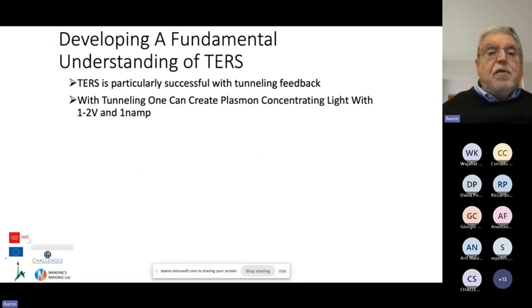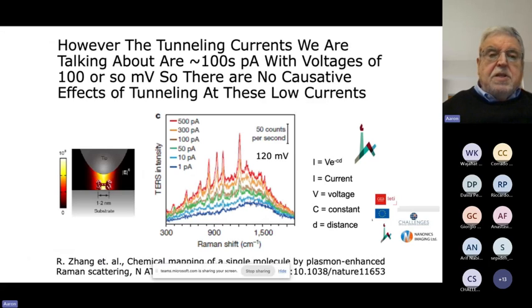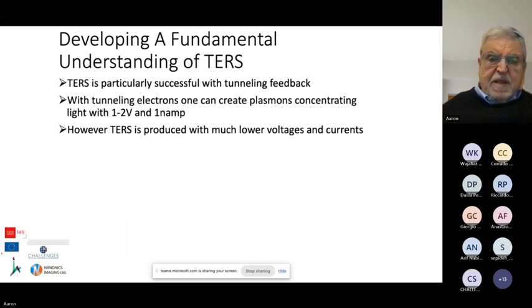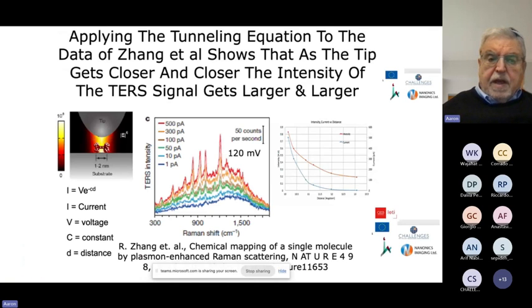Tunneling feedback can create plasmons. There can be a causative effect, but that causative effect is at a very large voltage, okay? And a very high current. Basically, TERS occurs at much lower voltages, millivolts, and in picoamp currents. And as you change the current from, say, 1 picoamp to 500 picoamps, on the same material, the TERS signal starts to increase. But notice, the value of the band hasn't changed at all, okay? So TERS is produced with much lower voltages and currents than the causative effect of tunneling electrons, okay?